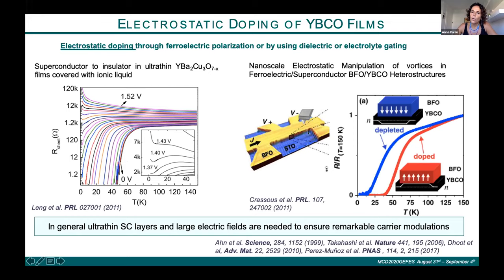the YBCO bridge, and they induce a transition in the YBCO by using the electric field gradient in the ferroelectric. And in this case, they were able also to modulate the vortex pinning in the material and produce reversible vortex pinning effects. However, all these systems in general use very ultra-thin superconducting layers, or they have to use very large electric fields in order to be able to see remarkable differences in the current densities and produce this drift from the superconducting to the insulating state.